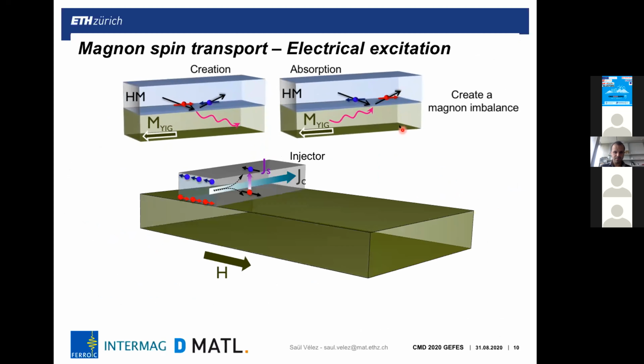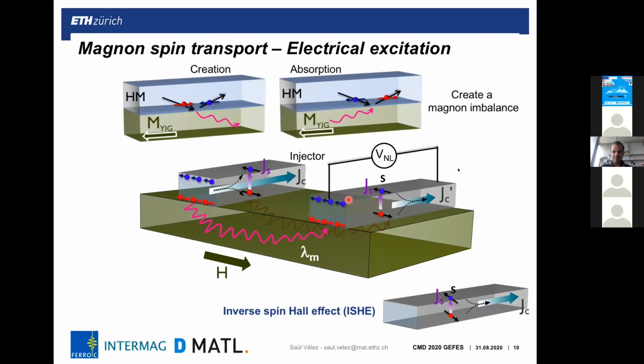So basically, we now have a platinum layer on top of the magnetic insulator. So we can excite magnons by applying a charge current, if we have the magnetic moment oriented parallel to the spins, and the propagation of these magnons can be detected non-locally in another platinum stripe, by having the opposite effect here. So we convert magnons to spin and the spin to charge current by using the inverse spin Hall effect.